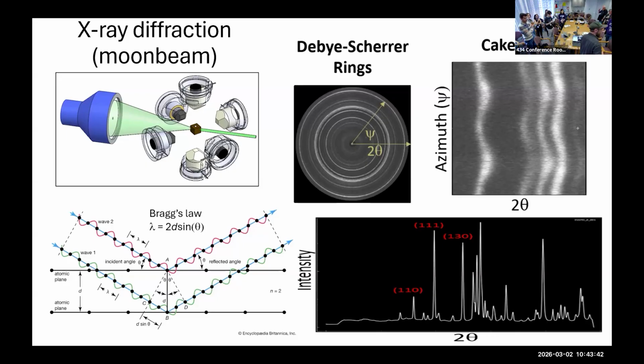Okay. So let's do it this way. We have our crystal, and you see the spots on the side. Those are where the diffraction patterns show up. So the laser's coming in, and then it's coming off at an angle to make a dot at that position. But now you'll have another grain at a different orientation, and it'll make a dot. You see that the outer dots, as I rotate it, they spin around, but they stay the same distance away from the center. You see what I'm saying? So then you're basically filling up the whole circle from a bunch of different grains.